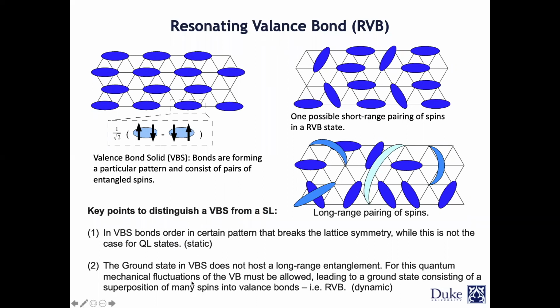Now, the ground state in the valence bond solid is not going to host long-range entanglement, while in the quantum spin liquid, it is true that you can have long-range entanglement, and these are the quantum mechanical fluctuations that lead to that. These quantum fluctuations are also present when you're looking at the resonance valence bond. So the resonance valence bond is also very dynamic. Here, in the case of long-range entanglement, you can see that not only is there no pattern, but also, for example, this spin here is entangled with a spin far away, or this spin here is entangled with this one.